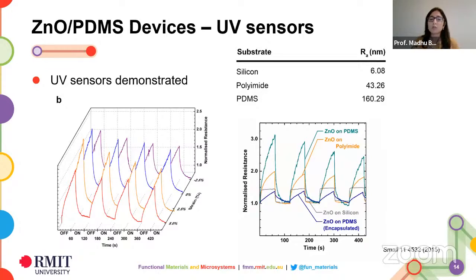Once again, you can see very good sensing performance, and we were able to understand that the reason the sensing performance of these materials is so high is because of the very rough surface which you have. So, the surface where you have the overlapping plates offers very high surface roughness, and that in turn translates to a much better sensing performance. So as you can see, the zinc oxide on PDMS has a much better sensing performance compared to, say, the same zinc oxide on other platforms where you don't have that high surface roughness.